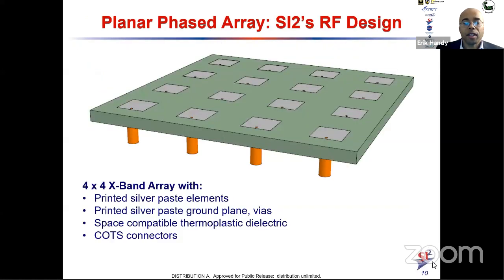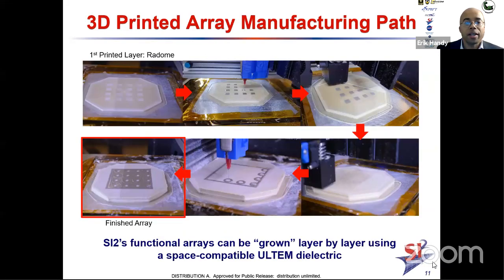Great, thanks. So just a quick look at what we did. This was the 4x4 array. The dielectric was space compatible ULTEM. The conductor was silver paste. So going clockwise from top left to bottom left through this montage, you can see as we print the radome first, this is out of ULTEM, and then we go back and forth between printing conductor and printing dielectric to achieve the full structure at bottom left there.